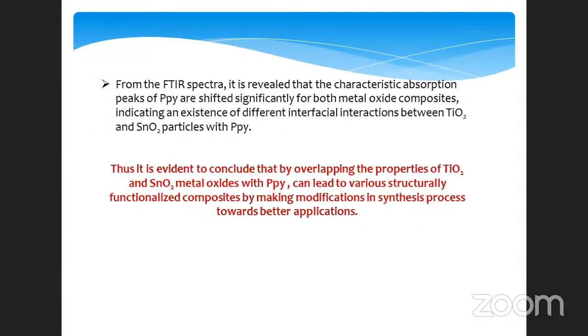Next, the TiO2, when composed into the polypyrrole matrix, shows that the anatase phase of TiO2 is predominant. From the FTIR spectra, it is revealed that the characteristic absorption peaks of polypyrrole are shifted significantly for both metal oxide composites, indicating an existence of different interfacial interactions between these metal oxides and conducting polymer polypyrrole. Thus, it is evident to conclude that by overlapping the properties of these metal oxides and the properties of conducting polymer polypyrrole, we can have modifications in the synthesis process towards better application. That's all from me. Thank you.